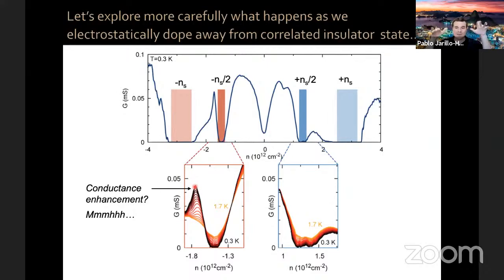That's okay if you are trying to measure an insulator, because if the resistance of your object is infinite, infinite plus something is still infinite. However, if you want to see how good a conductor an object is, and in particular if it superconducts, you actually need to get rid of that series resistance. So what we did is